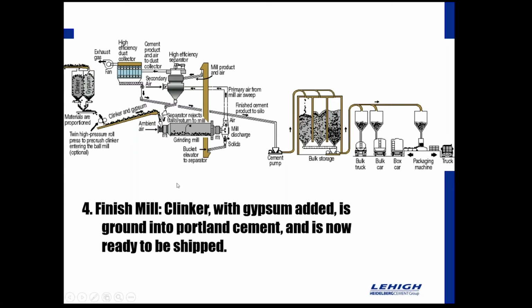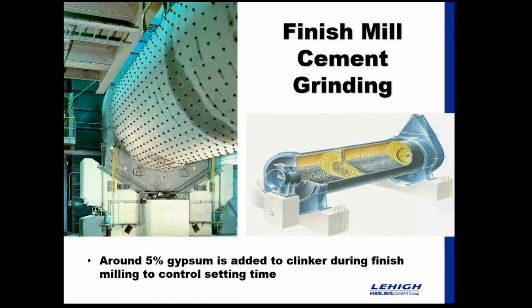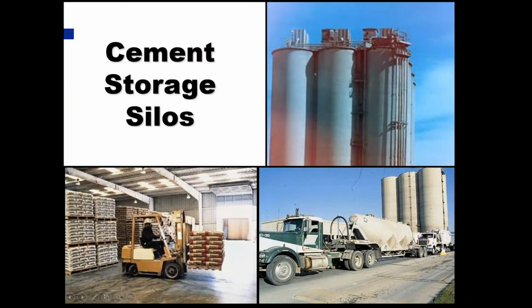So basically at this point, gypsum, about 5%, roughly something like that, is added to the clinker during finished grinding. And again, this is where from here now we're coming out with our final cement. And then once we have our cement ground, it goes to the different silos, and from the silos, it's either bagged or put into rail cars or put into tankers and then delivered to the actual producer.